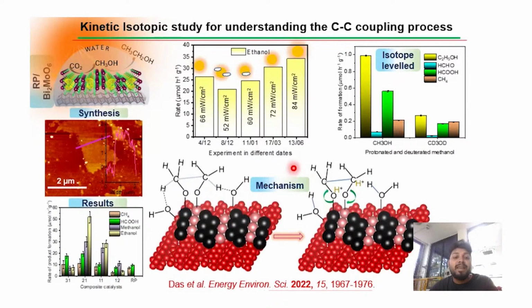Next, by importing very low cost red phosphorus material into bismuth molybdenum oxide, we have improved the CO2 to ethanol formation efficiency very largely. And you can see here, we have peeled the red phosphorus surface, and there we have deposited the bismuth molybdenum oxide, and in the composite 2,1, we got the highest activity reported so far. From this, we got encouraged and we studied the material in direct sunlight, and it is performing well in direct sunlight in different weather conditions.